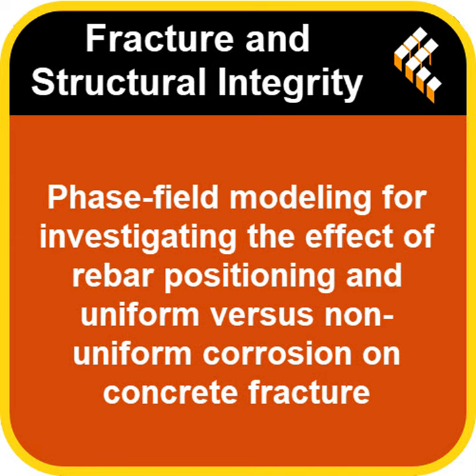By understanding how these different rebar arrangements respond to uniform versus non-uniform corrosion and the critical role of cover, engineers can potentially make smarter choices, maybe optimize rebar placement. Not just putting it anywhere. Right. Optimize placement and ensure adequate, consistent cover thickness to try and minimize weak points where corrosion could initiate damaging cracks. It helps refine design guidelines. So it's not just about the quantity of steel, but really the quality of its placement and protection, and thinking about the way corrosion might attack it.